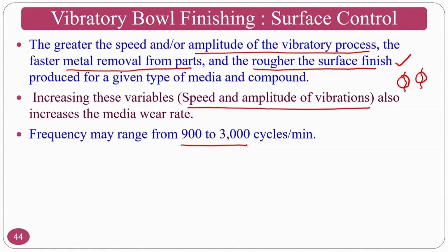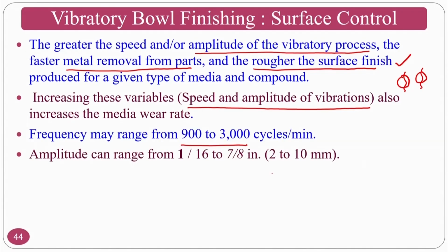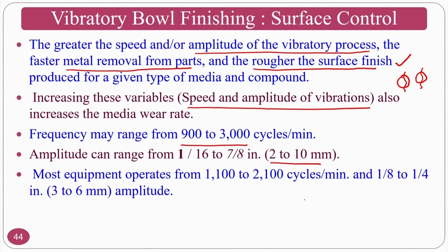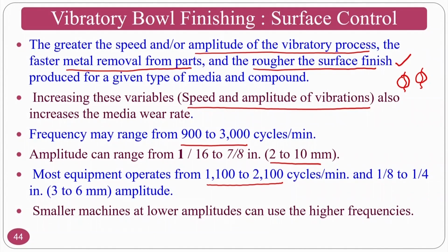Frequency may range from 900 to 3000 cycles per minute. The amplitude can range from 2 to 10 mm vibrational amplitude, and most equipment operates from 1100 to 2100 cycles per minute, at the same time with 3 to 6 mm vibrational amplitude normally. The smaller machines at lower amplitude can produce higher frequencies. So if people want to go for higher frequency with lower amplitude, you can even purchase small equipment. Small equipment, I mean small vibratory ball finishing processes.